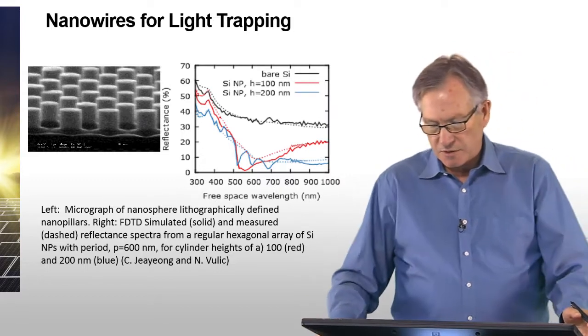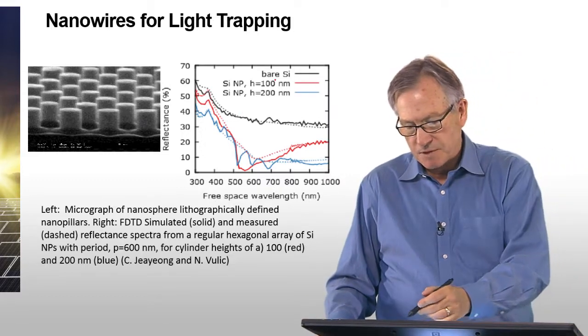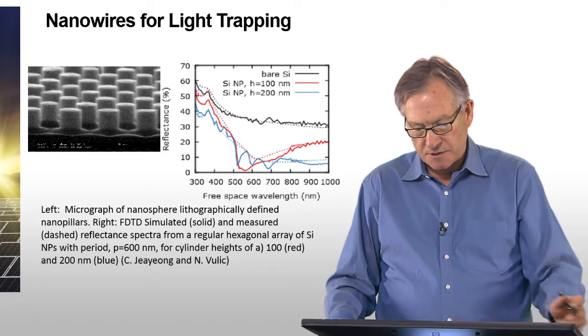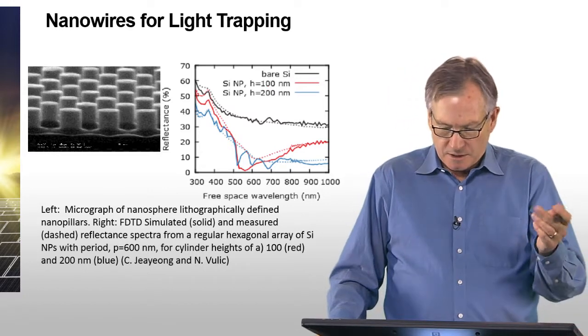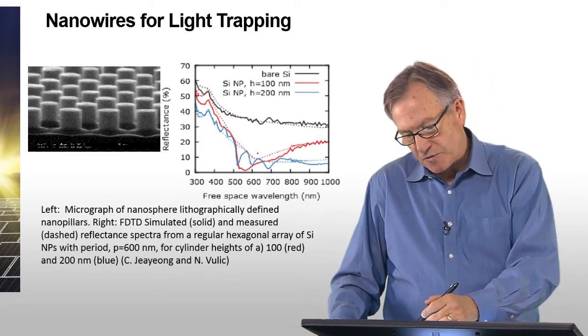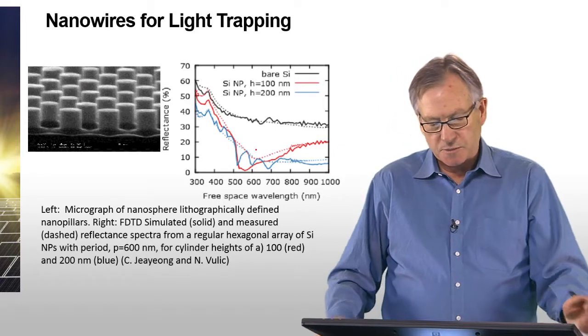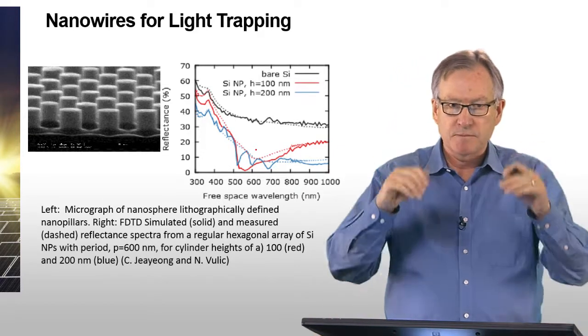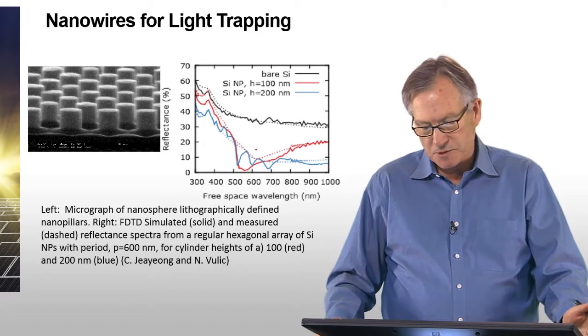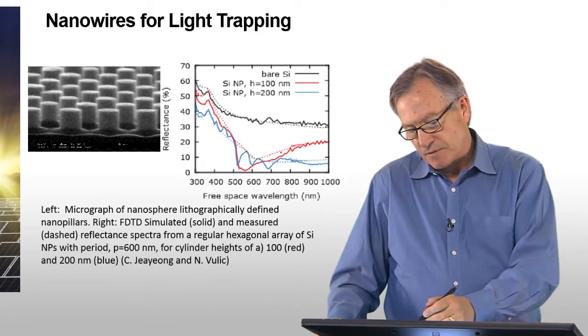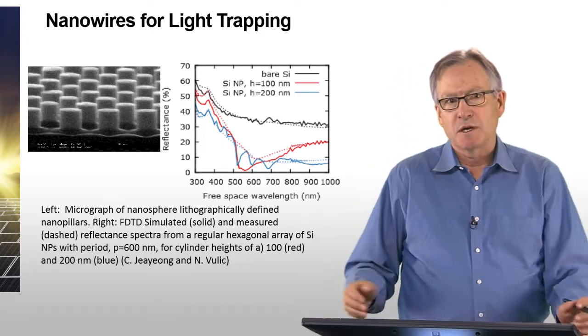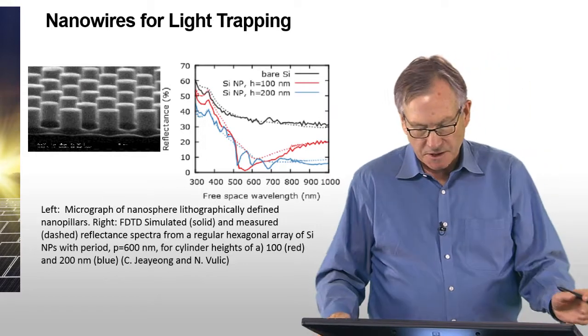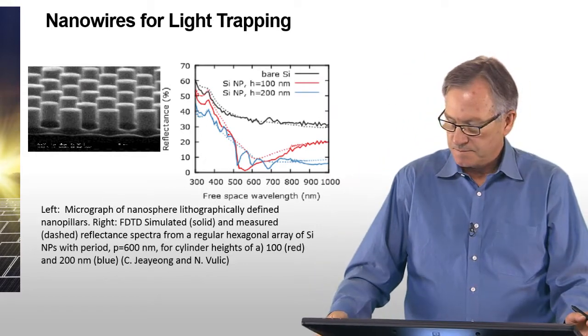In any case, this corresponds to bare silicon and two different heights of silicon nanopillars, and you can see, except for the fact that there's more features in the electromagnetic solution because it uses ideal, very sharp structures, there's a good agreement between the simulated reflectance and the actual measured reflectance.